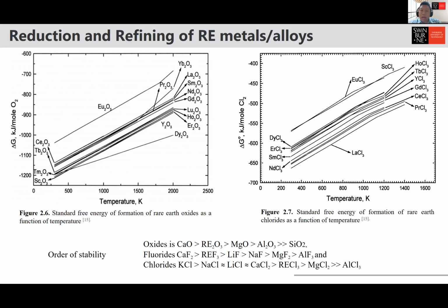Anyway, the one on the right is the standard free energy of formation of different types of rare earth chlorides as a function of temperature. Similarly, in terms of the delta G, they all lie close with each other, right? I also have a graph for the fluorides as well. So you can then put in the order of stabilities. For example, in oxide, CaO is more stable than RE2O3. And CaF2 is quite stable compared to REF3.